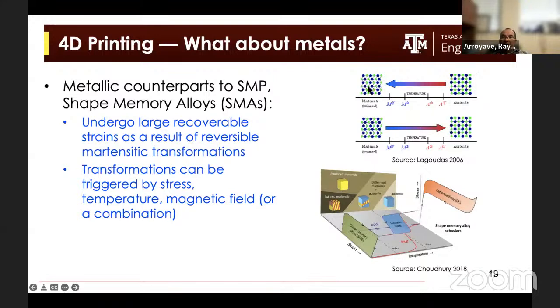So you have a martensite at low temperatures, for example, and as you increase temperature, there is a rapid martensitic transformation that takes this crystal structure and transforms it into a higher symmetry structure. And in shape memory alloys, this martensitic transformation is actually reversible and can be triggered by stress, temperature, magnetic field, or a combination of all these different types of stimulus, right? So shape memory alloys, they actually can undergo these reversible phase transformations.